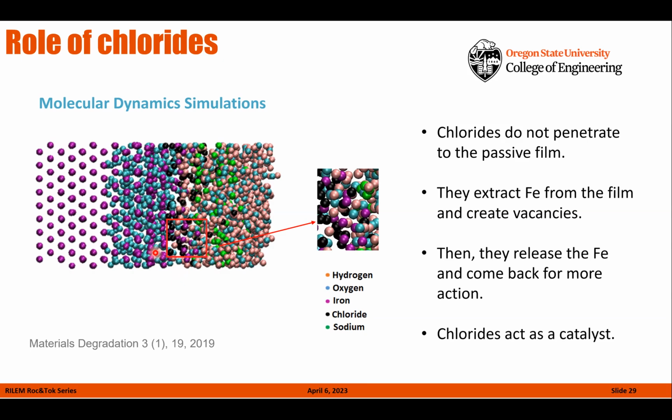So in a way, this gives us some indication that the mechanism might be more like the point defect model than the ion exchange model. So this is an important conclusion, or observation, that we can make from molecular dynamics simulations.